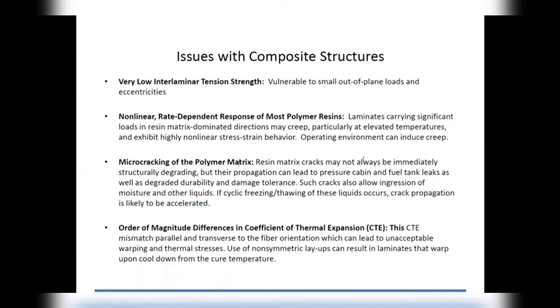Another consideration to keep in mind is that when you're manufacturing composites, depending upon the stacking sequence, you may find that since there's a mismatch in the CTE parallel and transverse to the fiber directions, you can introduce unacceptable warping and thermal stresses, especially if you use non-symmetric layups. And if you're using these kinds of applications in spacecraft, which are supporting a mirror or something like that, that's where this could be a potential concern.